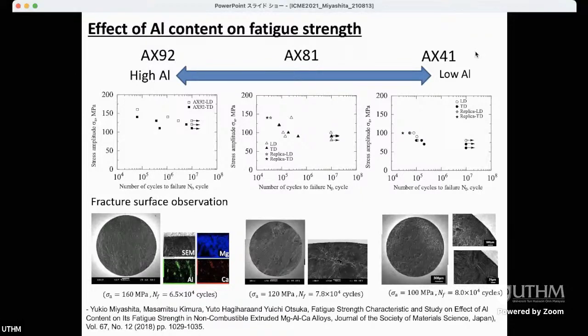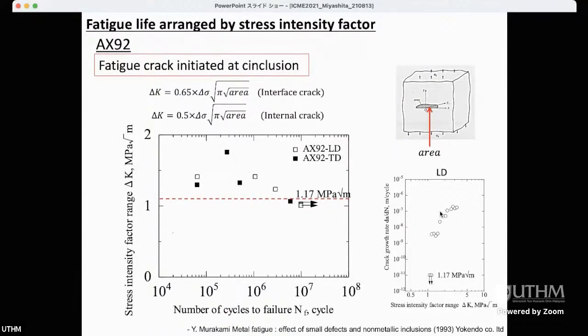As I already said, the mechanical property, also fatigue strength, depends on the aluminum content. However, in the case of the alloy including high aluminum content, we can recognize this kind of inclusion at the fracture surface, but not in the alloy with low aluminum content. And if the alloy includes quite high aluminum content, fatigue crack started to initiate from inclusion. This figure is a kind of S-N curve, but arranged by the stress intensity factor.